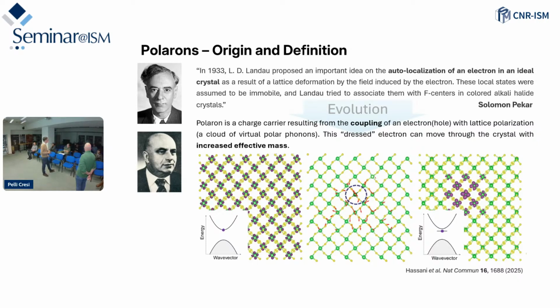It depends on the value of lambda. In this case, you need to introduce nonlinearity. You model it in order to fit your experimental results. In our case, the approach was a little softer. We saw only the deformation of the lattice, small polarons, yes. And this approach was confirmed also by time-resolved EXAFS, when we saw the effective